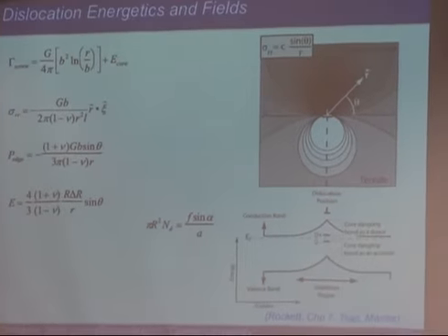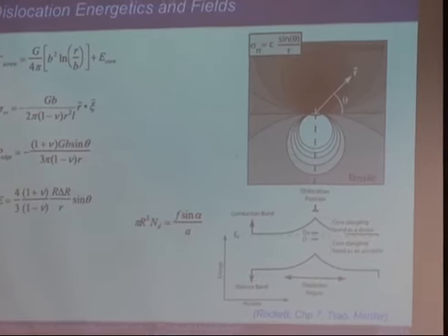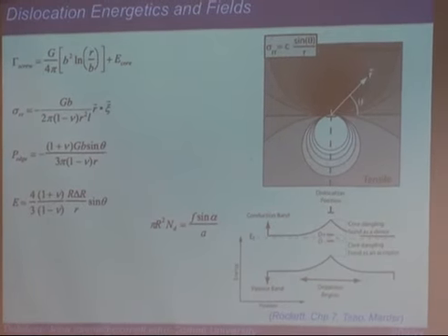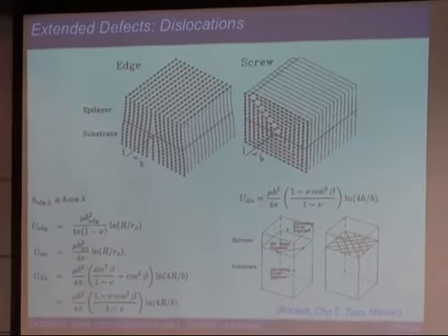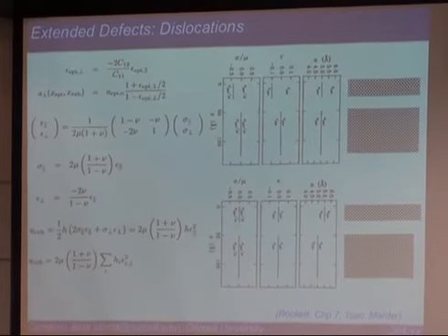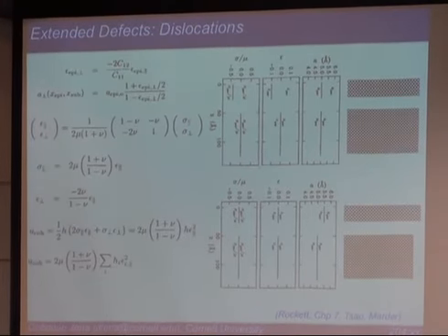So as you go around, this may look like a theoretical construct, but if you actually are doing TEM and you do a geometric phase analysis, you will pick out this dumbbell shape. It's very nice. If you have an edge dislocation, it will show you this exact feature, right? In our group, we do a lot of growths where we see that sort of dislocation, and that's typically a fingerprint that you got it there.